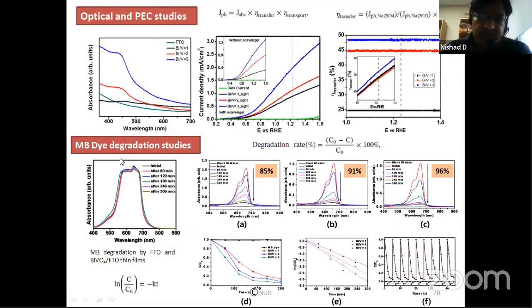Not only that, at the same conditions, we just introduced some methylene blue into this reaction, and with just FTO, there is no change in the absorption, but when we utilize our structures, what we can see is that at 300 minutes there is 85, 91 and 96. So this means almost 96% degradation is taking place with the combined facet structure of bismuth vanadate. We also tried to see the utility, or the stability.